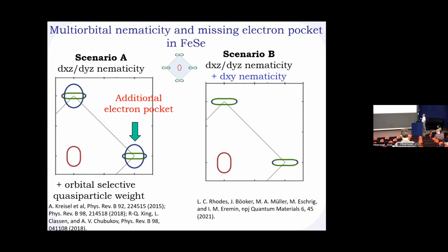Now, in the other scenario that we proposed, if you assume that the DXY nematicity is the largest player in the game, you can very nicely get a quantitative agreement with the Fermi surface found in the experiment. And also, something that I have no time to show, but you can see, is that you can get very nicely all the superconducting gaps, asymmetries, and so on and so forth.